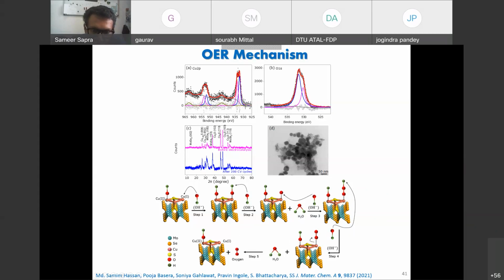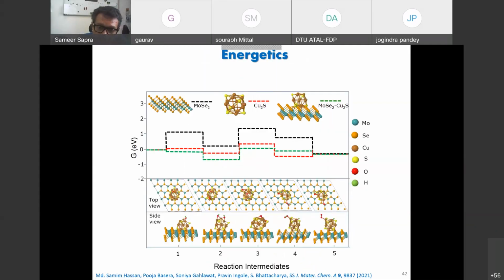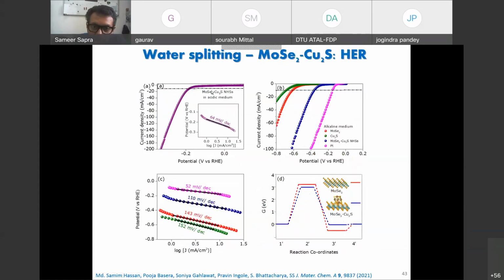So this is our proposed catalytic cycle, and this is also calculated by Shashwata to be a low energy pathway. Okay, very interesting calculations when you draw all these and you make all these structures and do all these calculations. So it comes out to be a very low energy pathway. The same we can do for HER. As I had shown you earlier, it was about 200 millivolts, slightly less for the heterostructure, 190 millivolts.